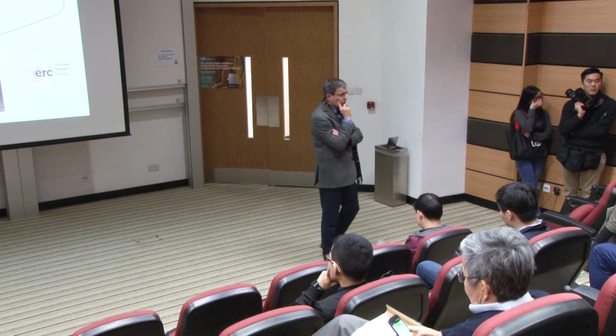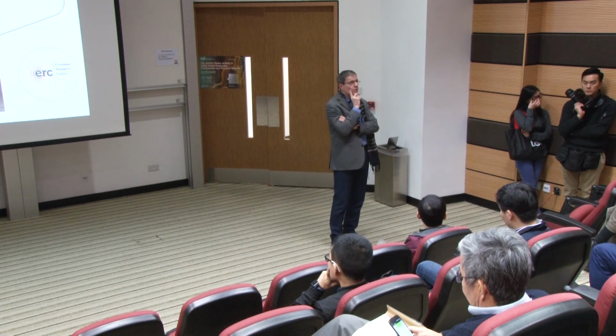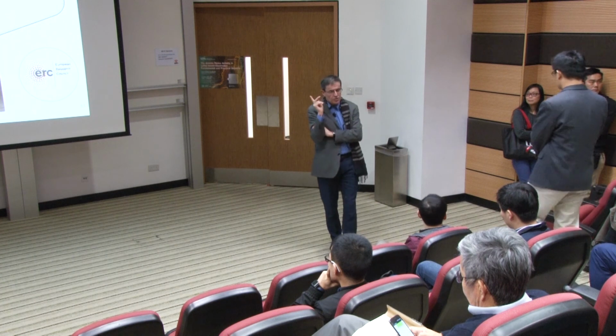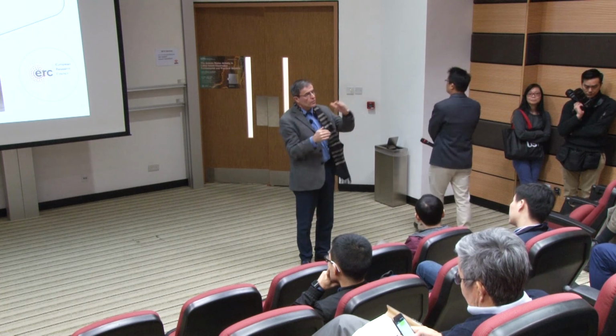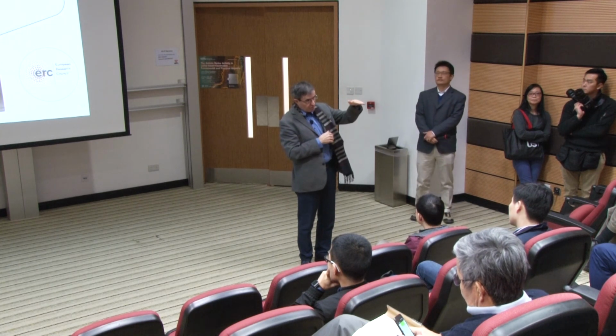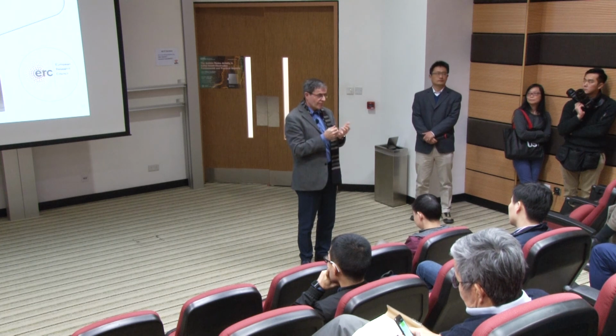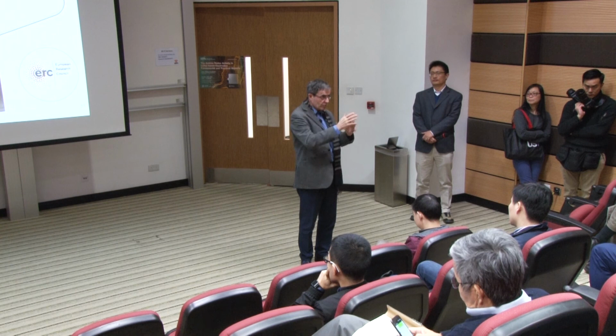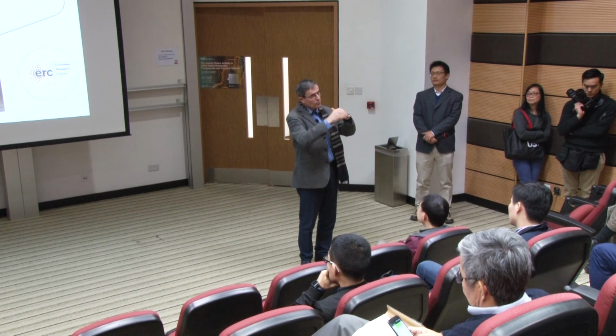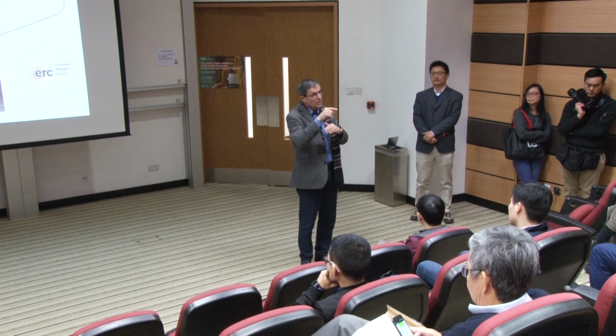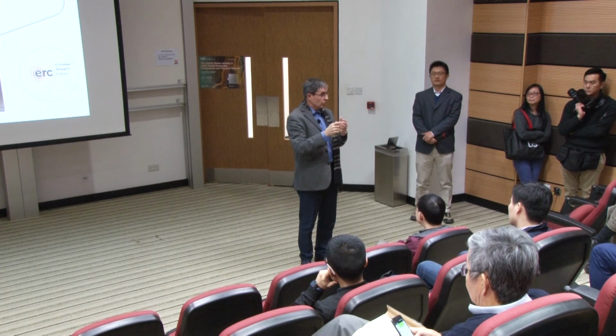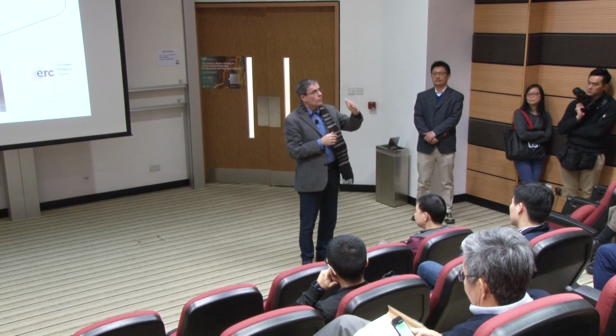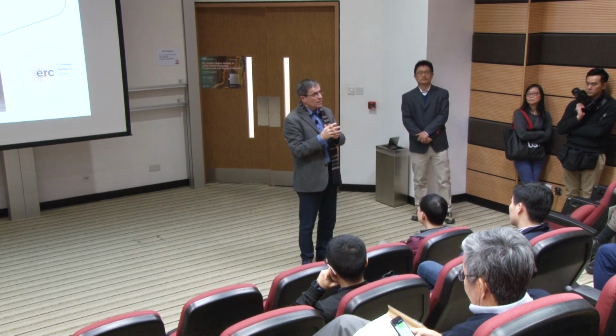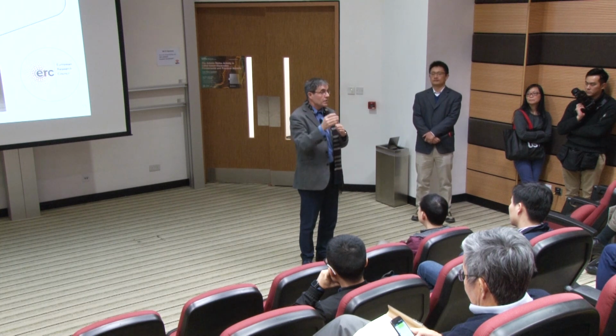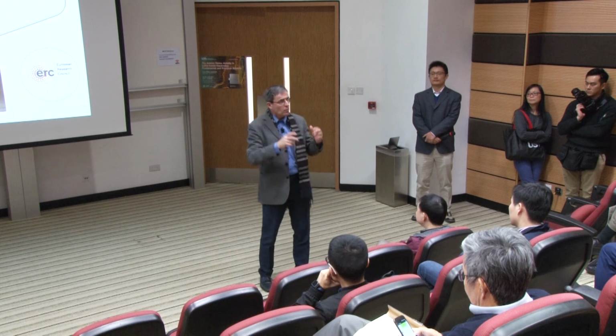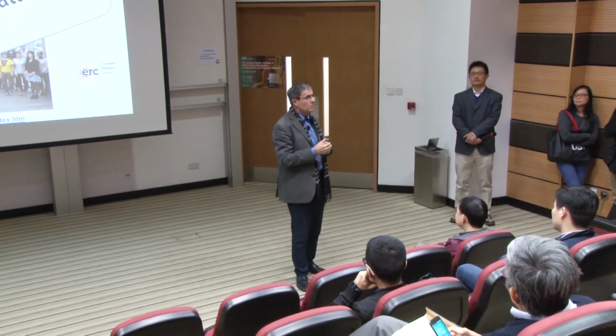I think the reason here we ascribe it simply in terms of cation size. And as I showed in the picture, when you take titanium, we can see, remember the picture, where I have these two spots, we have cation migration. Because remember, when we have this kind of oxygen activity on charge, we have migration of the cations. So the cations move from the van der Waals gap to the metal layers. And when they move here, within the path, they go through a tetrahedral site. And what we have shown is that when you have a small cation, like titanium compared to tin, it can get trapped into this site. And this is more or less what happened in the case of manganese, which is even smaller, it gets trapped. And here, we have also this kind of transition, what people call a spinel-like layer. And I think more or less this is the reason why.